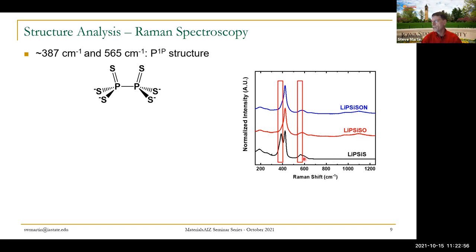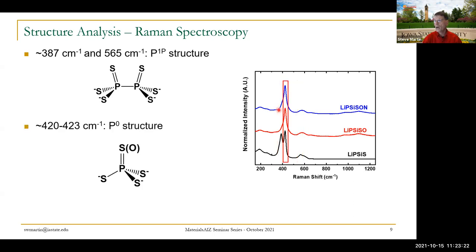What I want to highlight is this peak right here, which is associated actually with a defect structure. There's supposed to be a sulfur in there. And that defect structure does two things: it increases the electronic conductivity because of that phosphorus-phosphorus bond, but it also increases the reducibility of this glass. And so as we add oxygen and as we add oxynitride, it decreases that defect band, which is important. What is left behind are these things called P0.